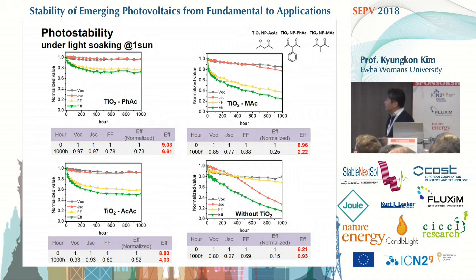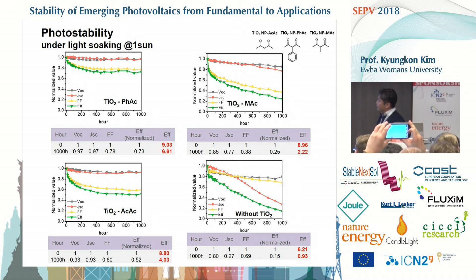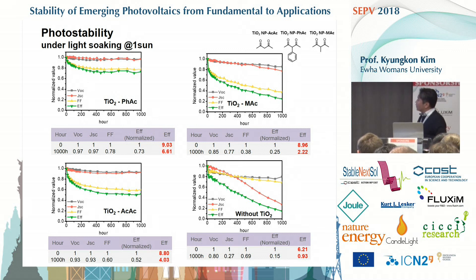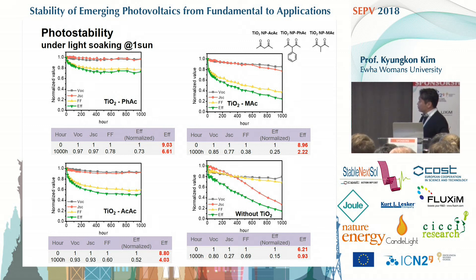If you plot this performance as a function of time, you can see clearly that in the case of phenyl-acac, it maintained about 73% of its initial performance. However, in the case of the methyl-acac material, it lost 75% of its initial efficiency, and the acac material is in the middle between these two. In the case without titanium dioxide, it decreases continuously and only shows 15% of its initial efficiency.